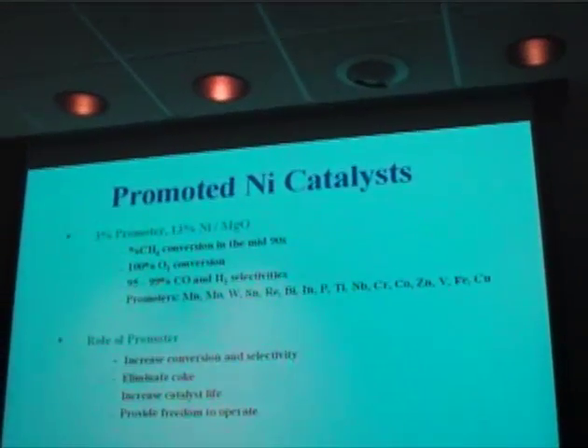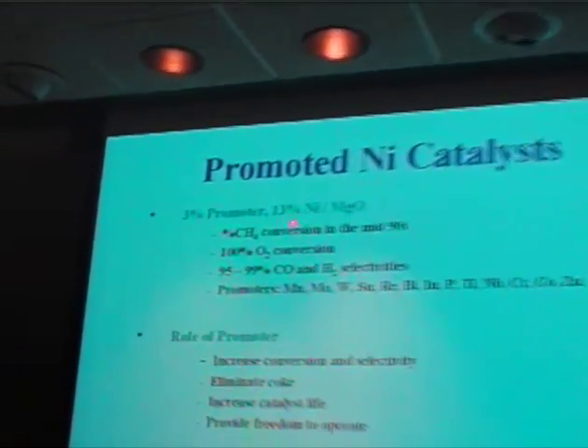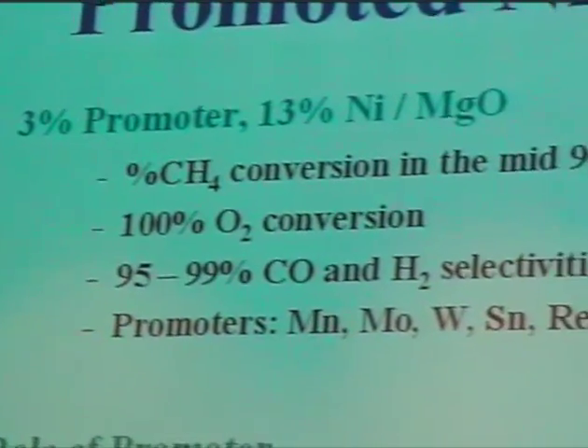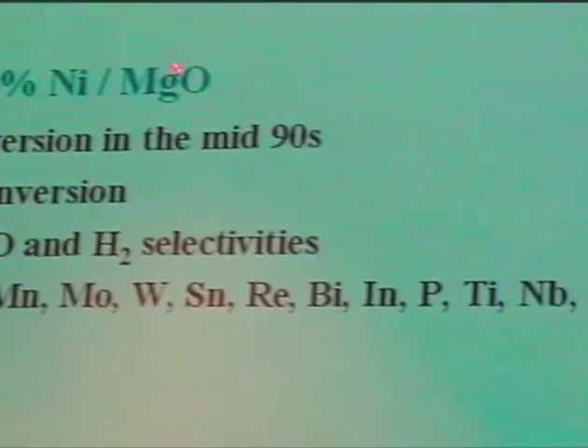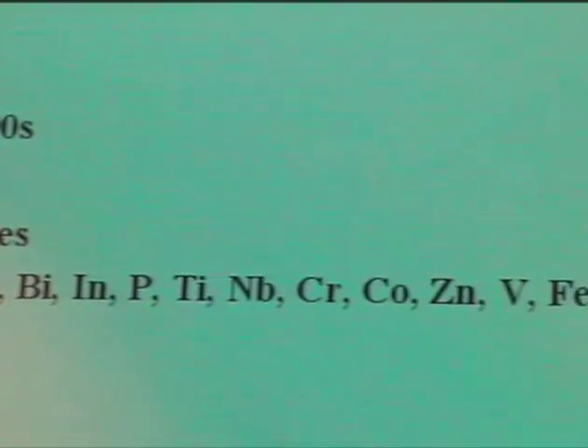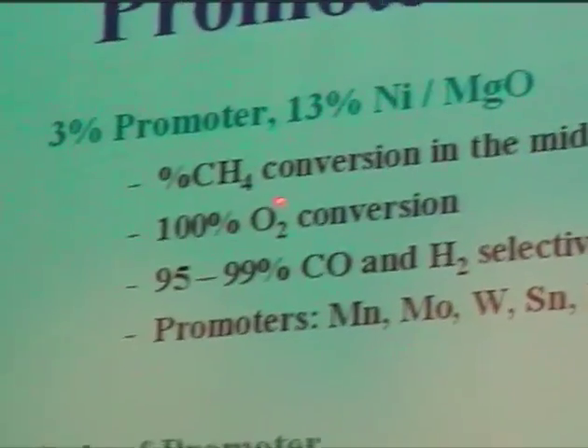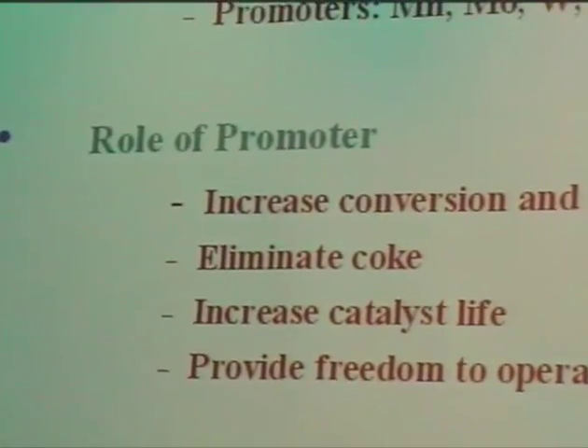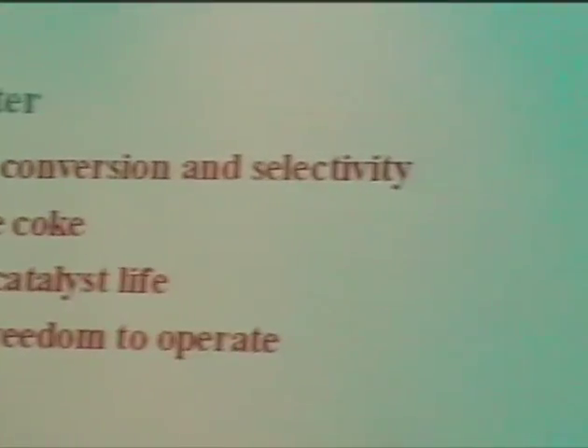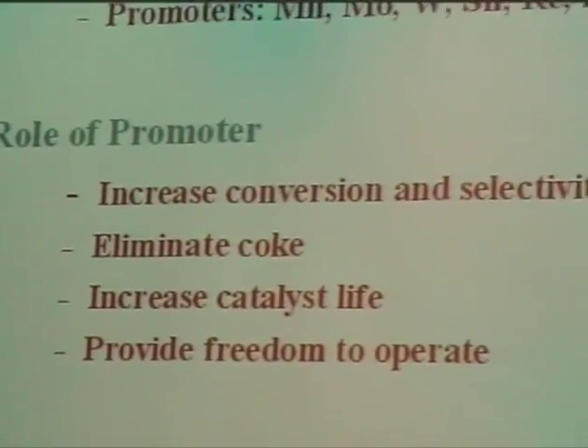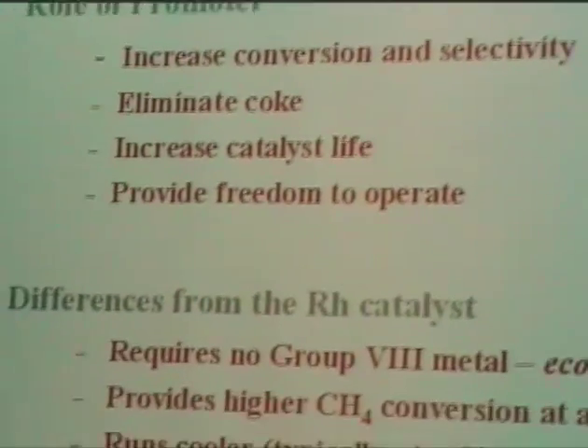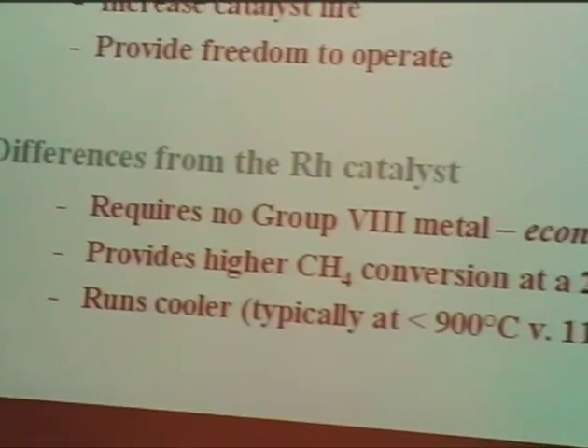So most of the catalyst data you hear today will be nickel with a promoter and with an MgO support. Really, it becomes a solid solution, and you'll see the data for that. The methane conversion would be in the mid-90s. Quantitative conversion of oxygen, which is good for safety purposes, and attractive CO hydrogen selectivities.